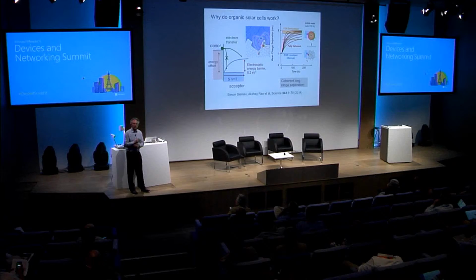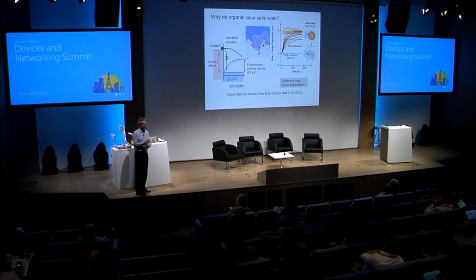And what we discovered is that for the systems which work well, the electron and the hole separate, and there isn't a length scale on here, by certainly about 5 nanometers within 10 to the minus 13 of a second. The electron hole are traveling very, very quickly. They're traveling at about 10 to the 5 meters per second, but 10 to the minus 13 seconds is not a long time.